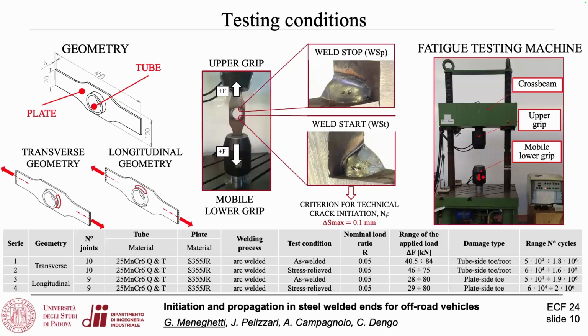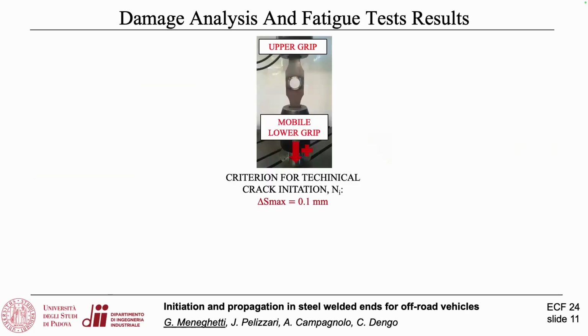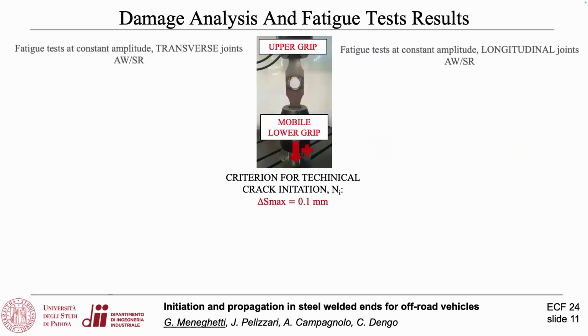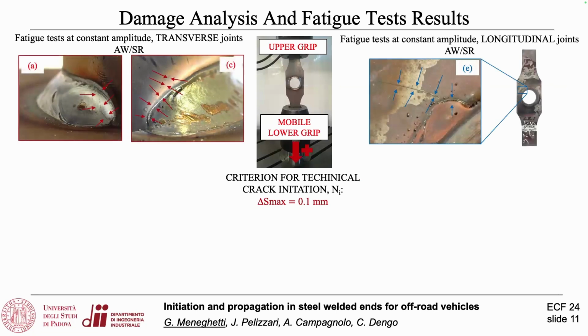stress-relieved conditions. And you see here the damage we observed in terms of crack initiation point at the tube side or at the plate side. But I will show this in more detail here. When we satisfied the crack initiation criterion, you see here the crack we observed. This is the transverse joint.